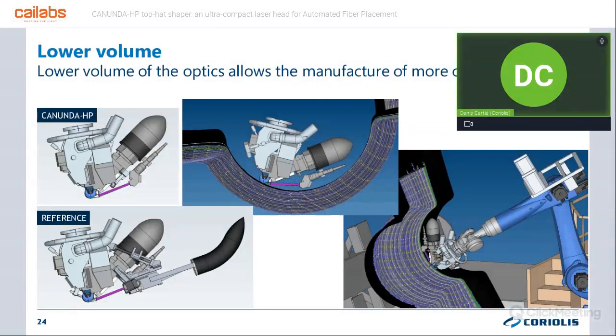Then just a few illustrations of why the volume is important. You can see here the simulation of the manufacture of a nacelle structure, and you can see that the part is very complex. With AFP, the head has to be able to roll inside the mold to be able to manufacture it. Large laser optics would dramatically increase the volume and bulk of the head, so that would limit us in terms of which parts we can make. So with the CANUNDA-HP optics, we can manufacture much more complex structures, like the one shown here.